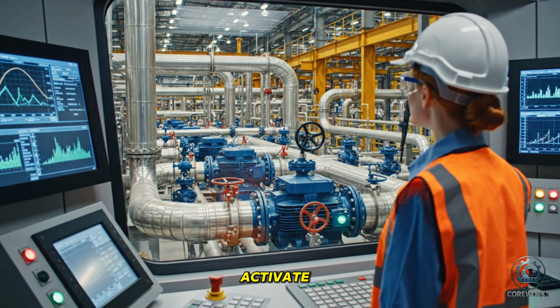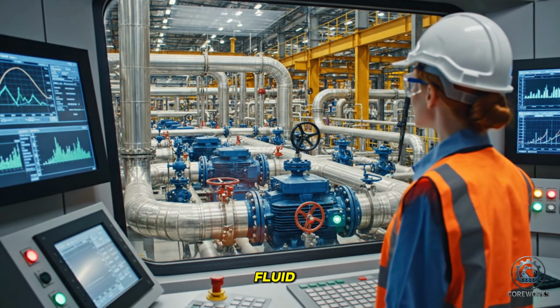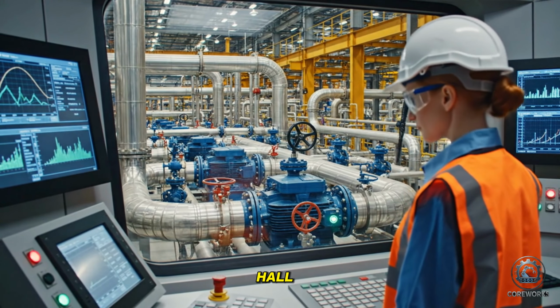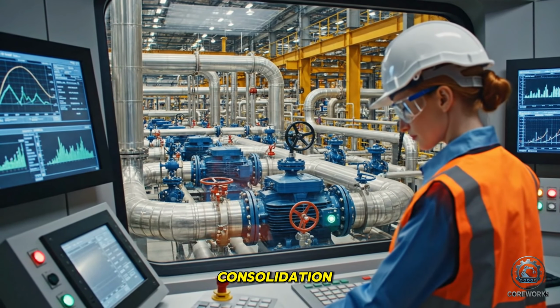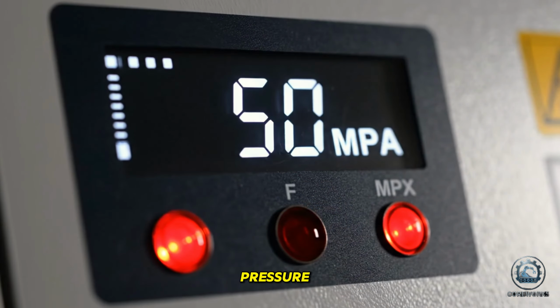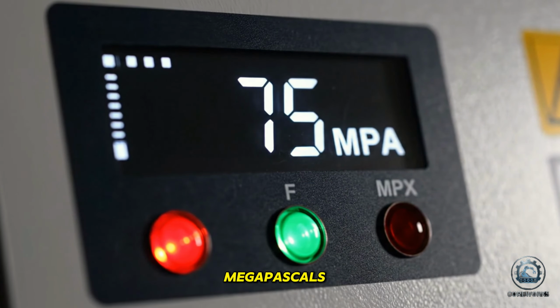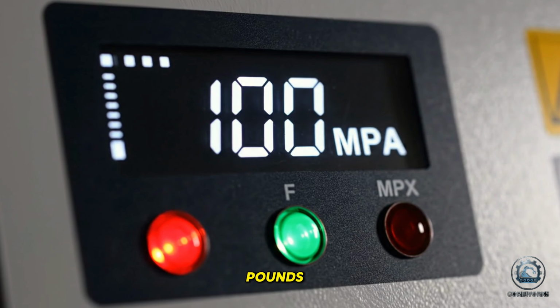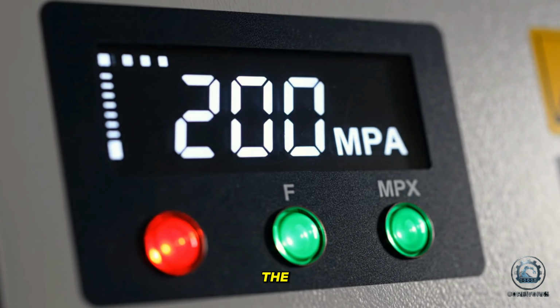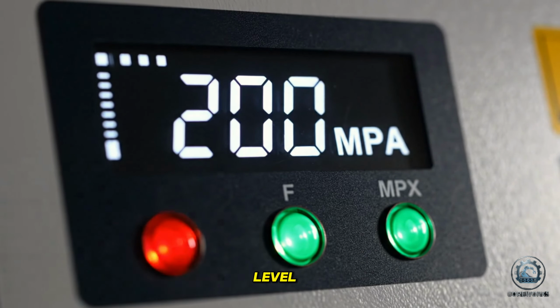As the pumps activate, the sound of high-pressure fluid filling the lines echoes through the hall, signaling the beginning of the consolidation phase. Pressure climbs rapidly to 200 megapascals, or nearly 30,000 pounds per square inch, forcing the particles to lock together at a molecular level.